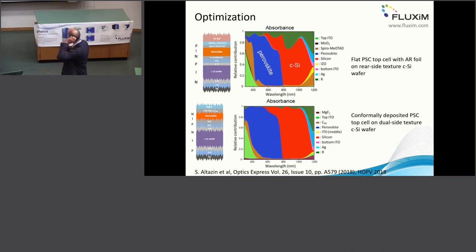Stacked contribution is just adding up all the contributions to the absorbance versus wavelengths, and you see the perovskite and crystalline silicon absorption. There's still a strong reflection here, the green contribution, that's just reflected light, that's bad. And in this structure we also have spiro-OMeTAD in the front, which has some parasitic absorbance that can be noticed in this brown area here, and also on that side.